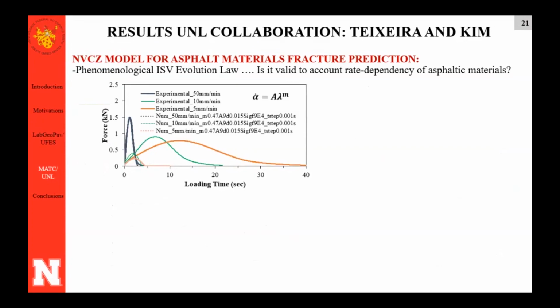And that was the result. So as you can see, for 50 millimeter, the curves from numerical and experimental match, but of course they match. I calibrated with 50 millimeter, okay? But then if I use the same parameters for other rates, I had this prediction, the green here and the orange here, that does not match with the green curve from the experiment and the orange curve from the experiment in other rates.